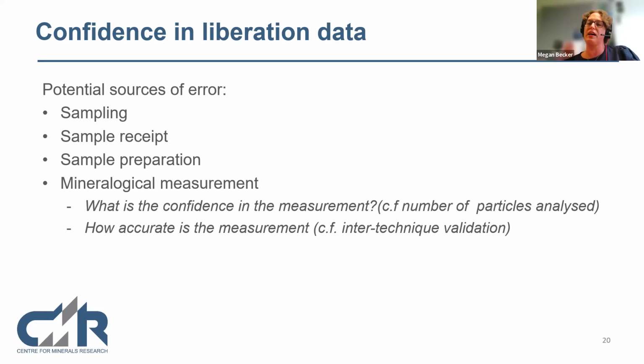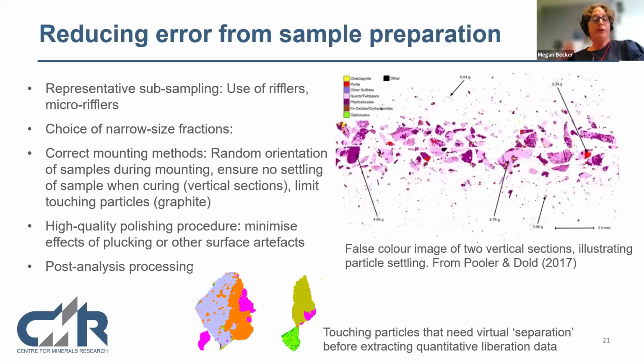This comes from something like how many particles have we analyzed, and then the other part is how accurate is the measurement. And the only way we can get confidence is by looking at other techniques, validating between different techniques. So how do we reduce error from sample prep? Obviously, I'm not going into sampling error. That's a whole other book of its own. We use things like representative subsampling, rifflers, micro rifflers, and we work with narrow size fractions.